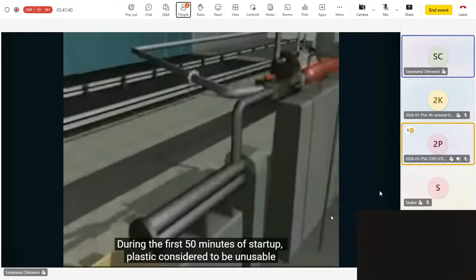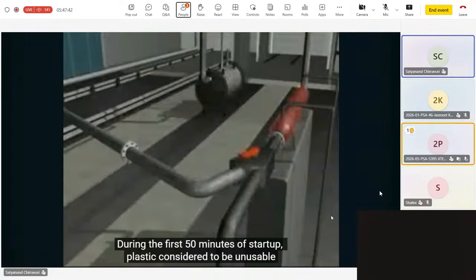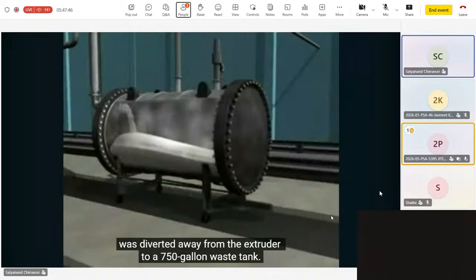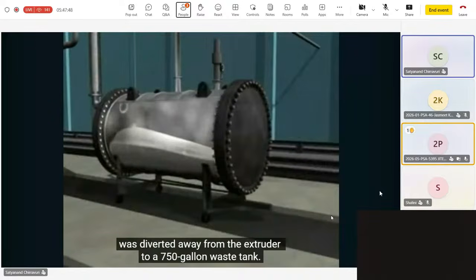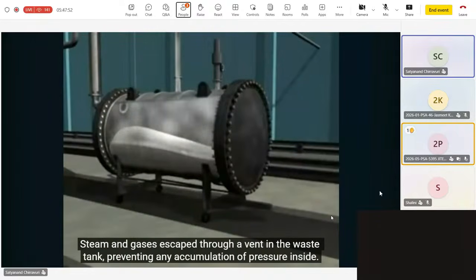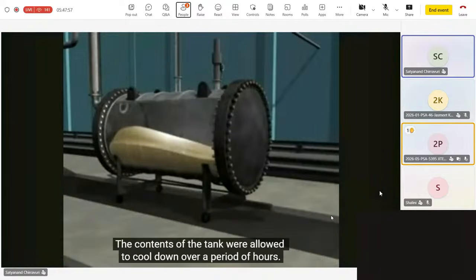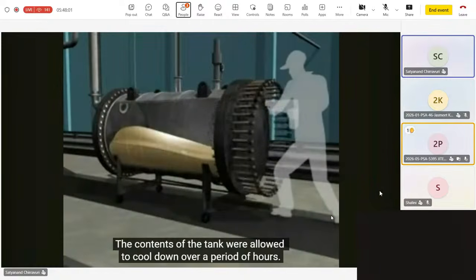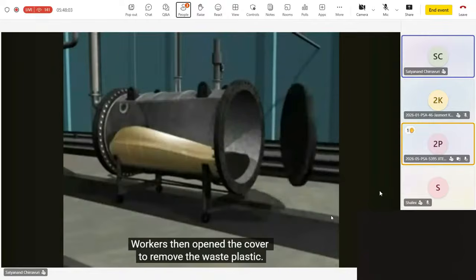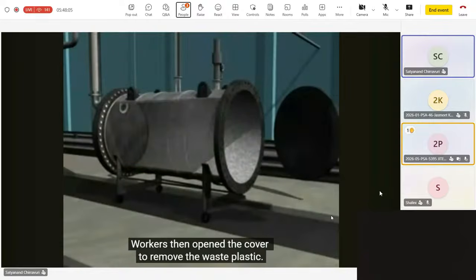During the first 50 minutes of startup, plastic considered to be unusable was diverted away from the extruder to a 750-gallon waste tank. Steam and gases escaped through a vent in the waste tank, preventing any accumulation of pressure inside. The contents of the tank were allowed to cool down over a period of hours. Workers then opened the cover to remove the waste plastic.